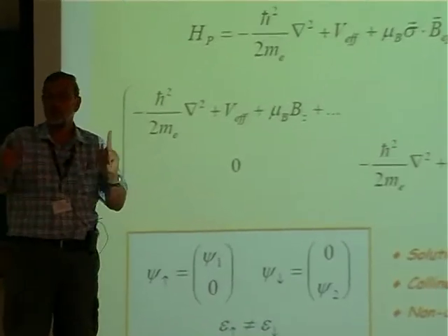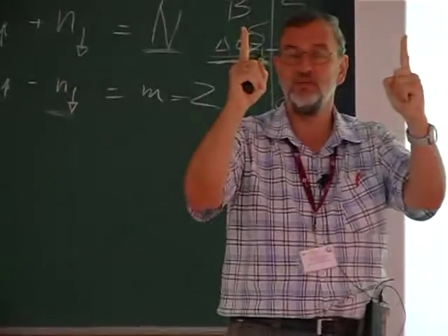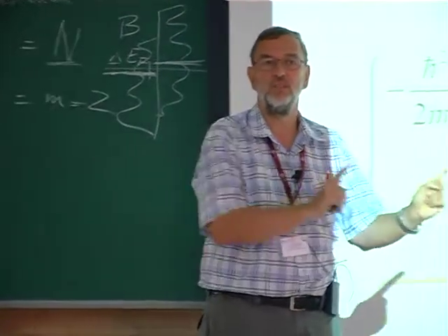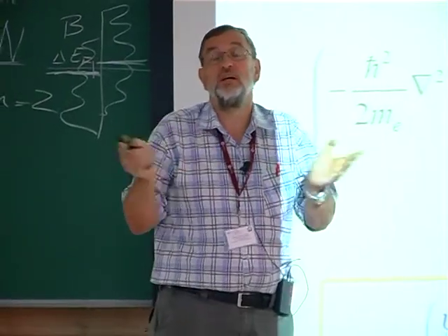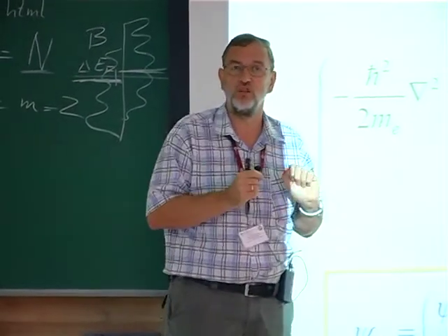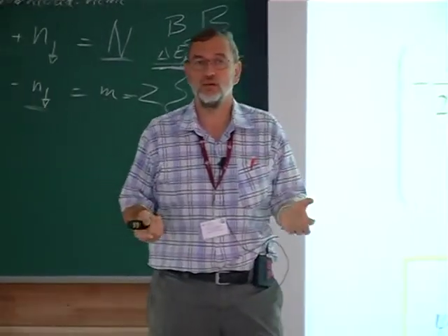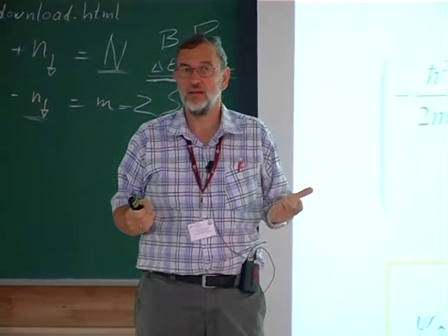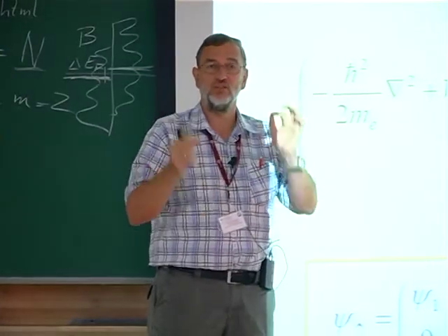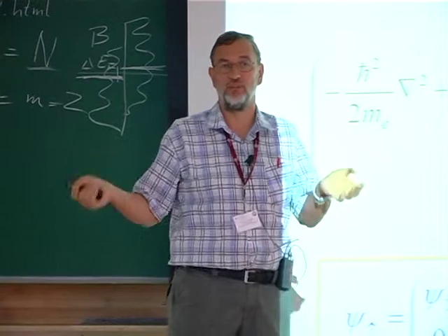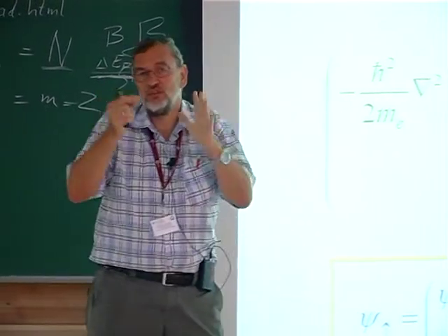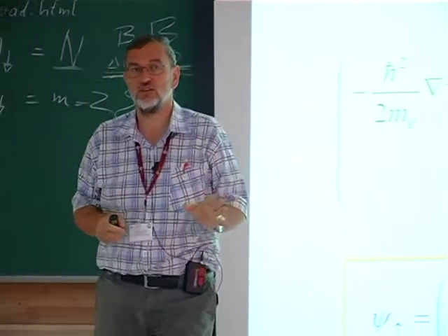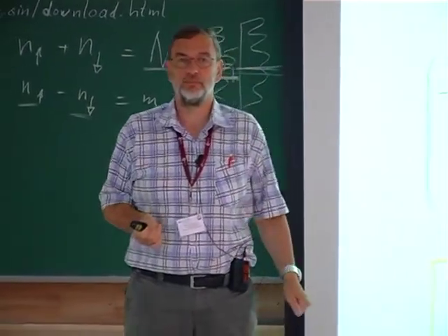Then we would do another calculation with both vanadiums spin up and compare the total energies between these two and see what is the better energy, that is the lower state. And then we could do a third calculation, make the calculation non-magnetic, and compare this third total energy with the two previous ones. And that gives us, in this search of collinear magnetic structures, the lowest energy.